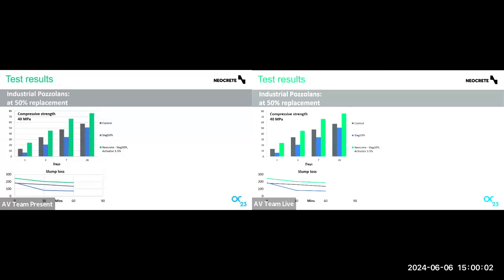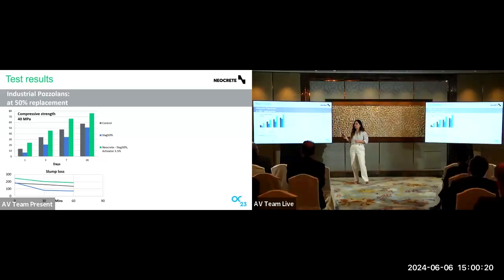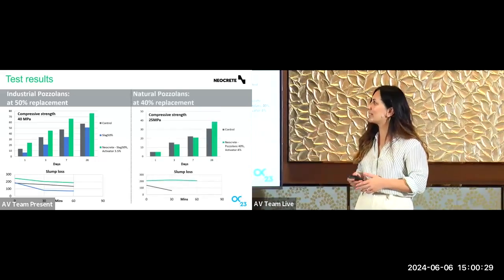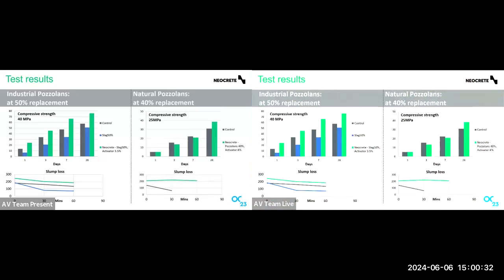On the left-hand side, you can see 2 controls: the CEM I cement-based control, and a 50% substitution level with the superplasticizers. And the green one is Neocrete at 50% replacement level with slag, and Neocrete activator at 3.5%. You can see that the activation is so significant that at 50% substitution level, we outperform the CEM I control concrete, not just match it. And then the other one is natural pozzolans. Natural pozzolans, for perspective, are not used in New Zealand currently in construction because they're considered low activity and not economic to be used. And we were able to provide 40% substitution levels and match the performance and outperform on day 28.